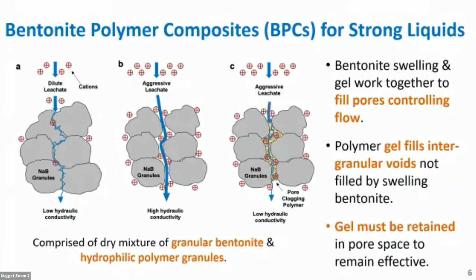And so if we think of on the left a conventional bentonite, if it swells, the granules swell shut and the liquid has to go through this tiny little pathway. Very impermeable. If the granules don't swell, we'll have a pathway that remains open and it's more permeable. And the idea with these polymeric materials was to add just a modest amount of hydrophilic polymer that would fill that pore space. So we'd rely on some swelling of the bentonite, and then where we had any remaining pores, we would fill that with polymer. And that's what gave birth to the bentonite polymer composite geosynthetic clay liners that are on the market today.